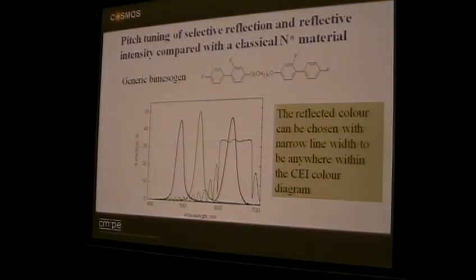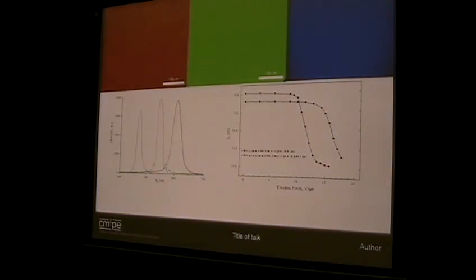No polarizers, no color filters. If you want to work in transmission, if you are perverse and you don't want to save energy, you can put these things between cross polarizers and you see exactly the same colors. Okay? And if you ask me again afterwards, I'll tell you why that is. But if you want to see that sort of spectrum in transmission with a polarizer analyzer, you can do that. You might want a transmission device. Purity of color, that's coming up, it actually is red on this, my screen, but R, G, B. Those are your spectral lines. Those are the colors over, in this case, I've just used about a millimeter pixels. I've gone up to centimeter square pixels.